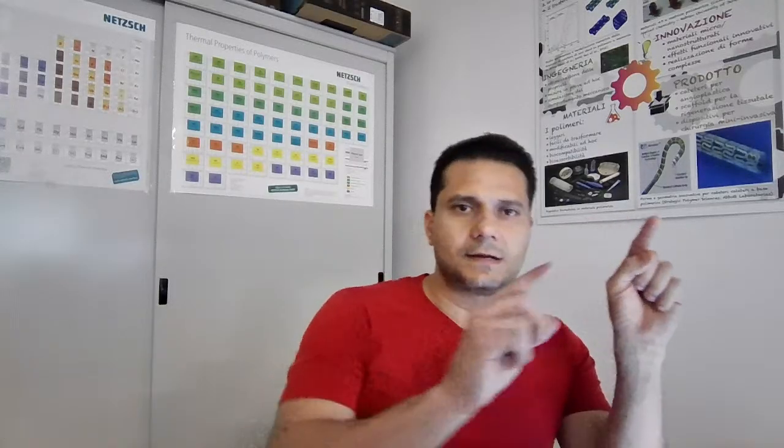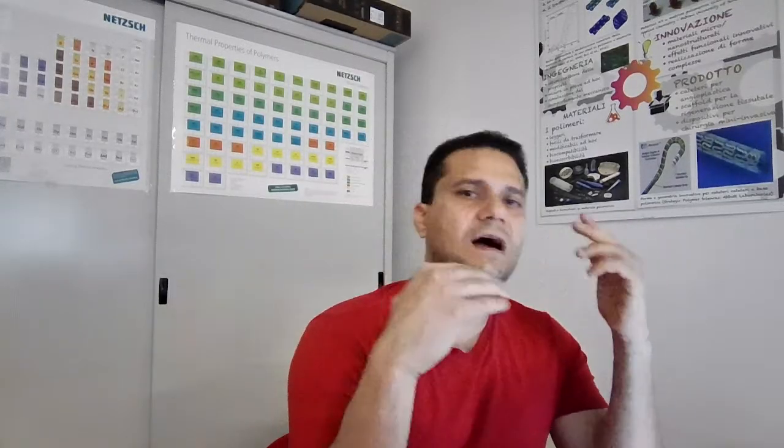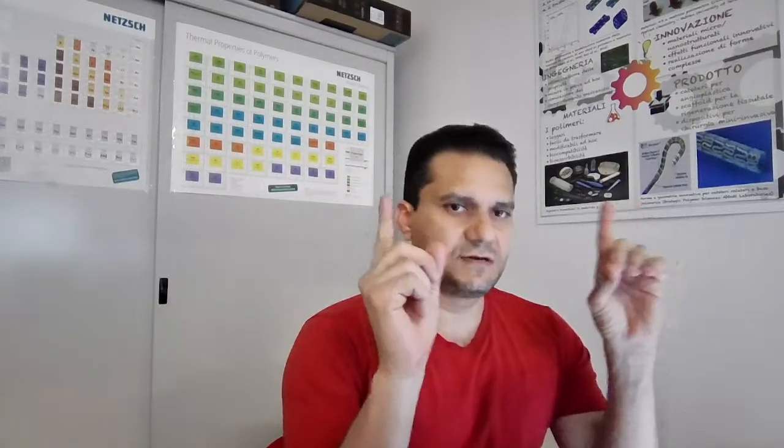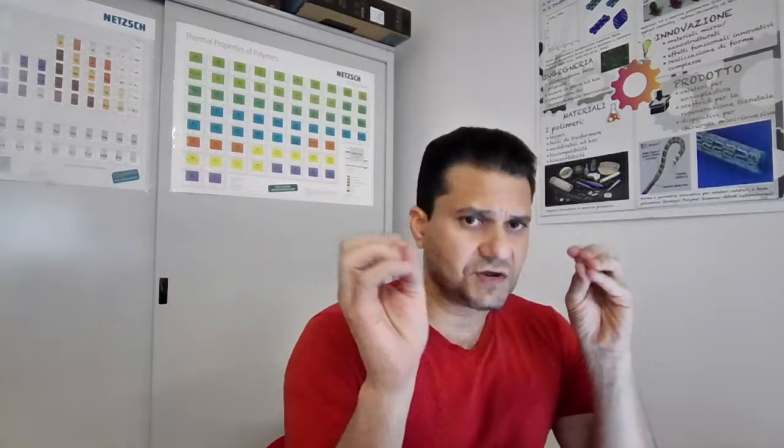Sure. So, in this case, assuming a self-affine fractal surface and a hard rough substrate, we consider a range of wave vectors to work with. Because if I keep increasing my magnification, I will reach a point where there is no contact area, because the contact area keeps reducing. So I need qL, the lower bound wave vector, and q1, the upper bound wave vector.